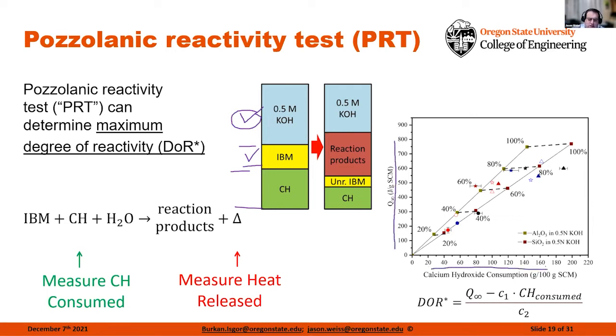Well, if we develop a plot of the heat that's generated on the y-axis versus the calcium hydroxide consumed, we can all of a sudden start to plot out where typical materials behave. And if we look at the pure fundamental lines that we should have on a graph like this, we see this line over here, which is pure silica reaction. This is just silicon dioxide reacting with calcium hydroxide. And on this line over here that I'll show as this dashed line, this is the alumina phase reacting with the calcium hydroxide.